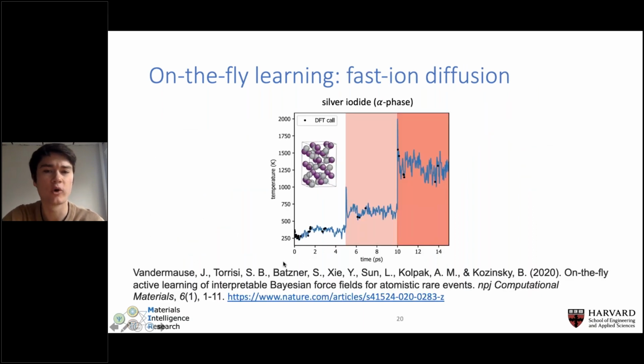Okay, so a slightly more complex system going beyond aluminum. This is the system I alluded to at the beginning of the talk. It's the fast ion conductor silver iodide, which exhibits kind of interesting structural and dynamic properties. So above 420 Kelvin, this system basically enters into a superionic phase where the silvers in the material start diffusing almost like a liquid, while the iodines are sort of rigidly located at their lattice sites. And we wanted to see if we could correctly model the fast ion behavior of this material.